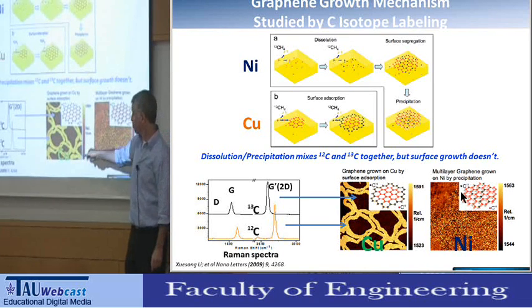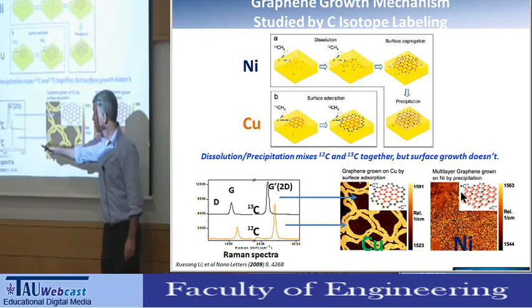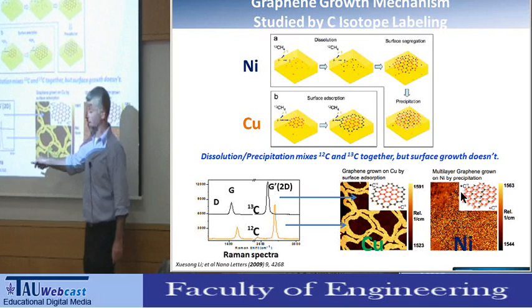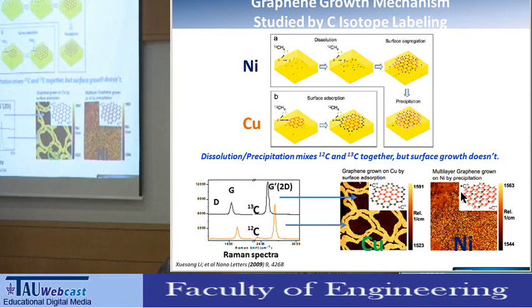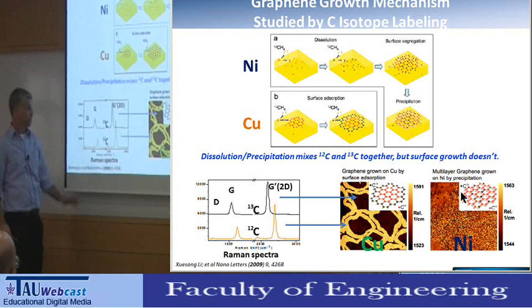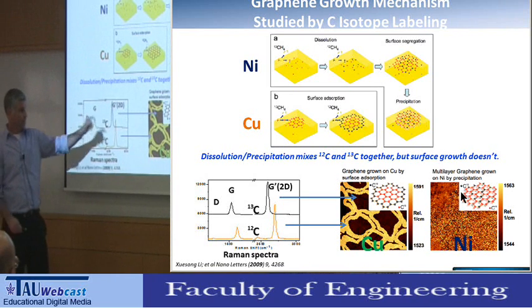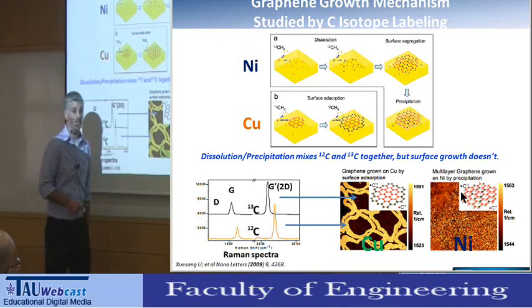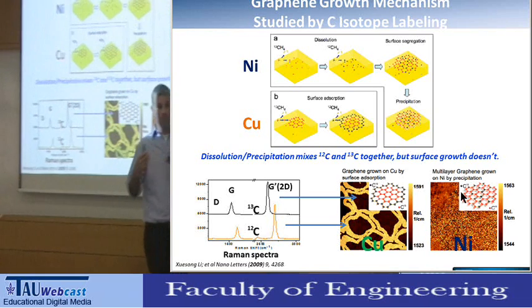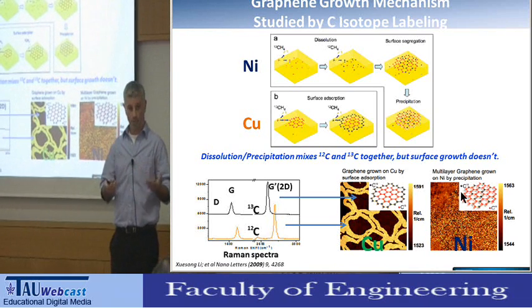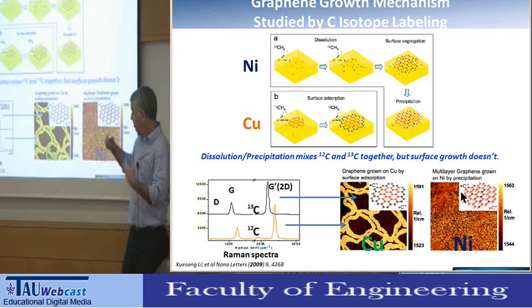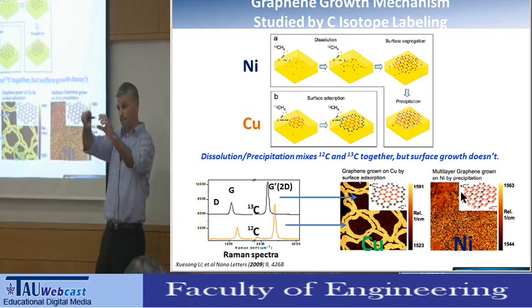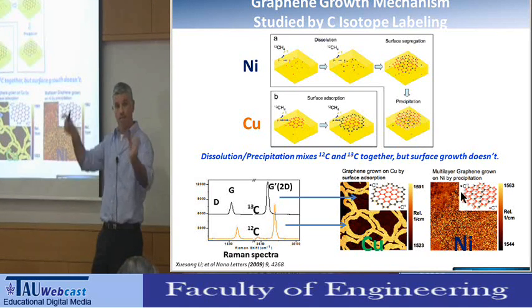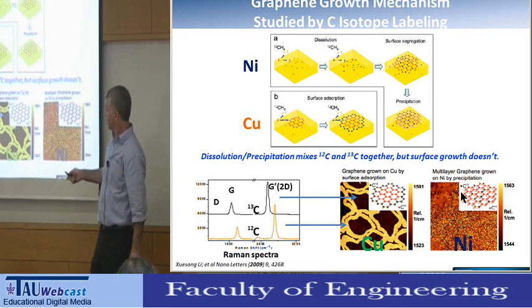This is a mapping with the position of the G band. Okay, you can see that there is a very clear shift in the band. So the dark area, the shift down, is the C13 enriched area. So it was the first, so this is the domain. Then you expose it to C12, so you get another stripe of C12 carbons attached to the domain.